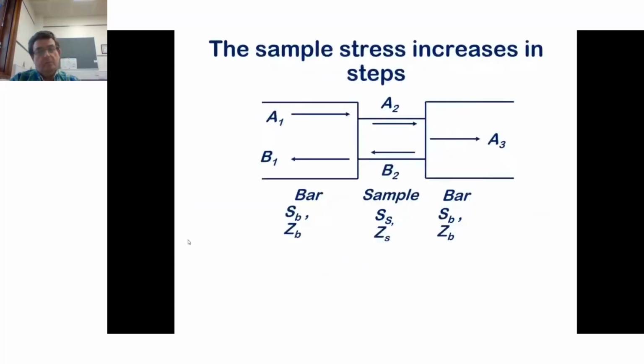And we also, looking in more detail, realize that this sample stress increases in steps. There are wave reflections occurring within the sample. Stress takes time to transmit. A wave speed in a piece of metal, say 5 millimeters per microsecond, 6 millimeters per microsecond. So it takes 2 microseconds for a wave to go through a 5 millimeter piece of sample and be reflected and come back to the input interface.